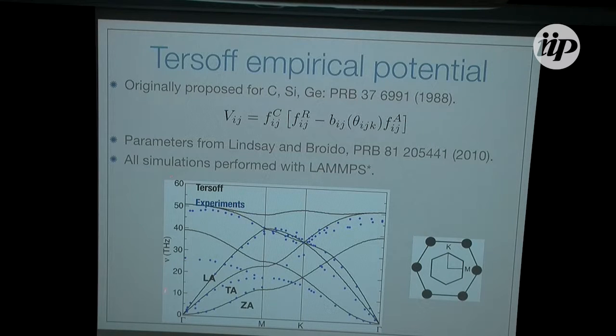So when we look at the phonon dispersion for graphene, right? These are experimental values from neutron scattering in highly oriented graphite, so in the in-plane directions, and the black curves are the prediction from the potential. So it's pretty good in describing this acoustic mode. Okay, it's not very good describing this optical mode here, but we're not really worried about it. The heat transport comes mostly from the acoustic modes, and most importantly, it gets the quadratic dispersion of this flexural mode correctly.